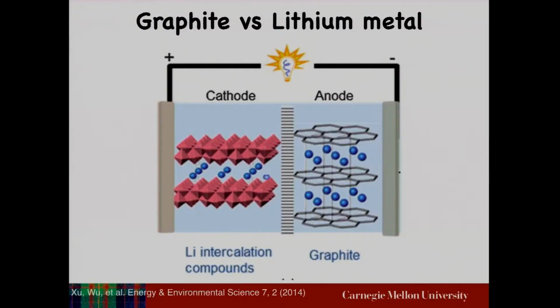And so I'll give you a 30-second version of how a battery works. Batteries have anodes and cathodes. The anode is graphite, and the cathode is some kind of layered compound or some kind of host material that takes the lithium ions. In the fully charged state, the lithium ions are inside the graphite. And when you discharge the cell, the lithium ions move from the graphite anode to the cathode, where they would rather like to be. And the energy difference between having lithium ions in graphite versus the host material on the cathode is how you derive energy.